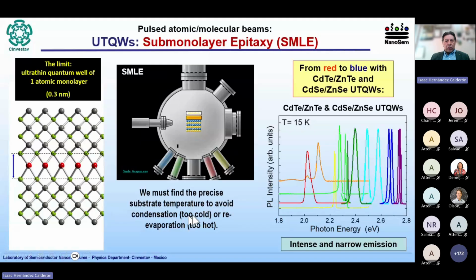For this, we must find the precise substrate temperature to avoid condensation if it's too cold, or evaporation if it is too warm. We have demonstrated that we can go from red to blue emission, not only blue-green, as most people know with these systems. We can go from red to blue with these ultra-thin quantum wells by using cadmium telluride and cadmium selenide quantum wells. So we can cover the whole visible range. And it's very interesting to realize that these very thin structures have an intense and also very narrow emission, highly monochromatic, not exactly monochromatic, but very narrow emission with very nice colors.